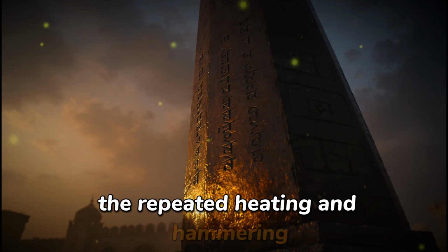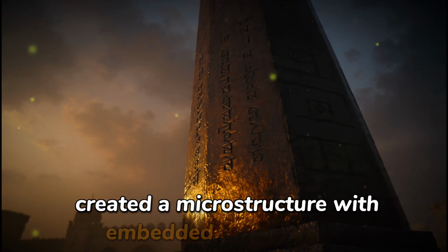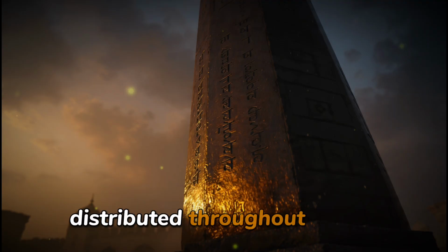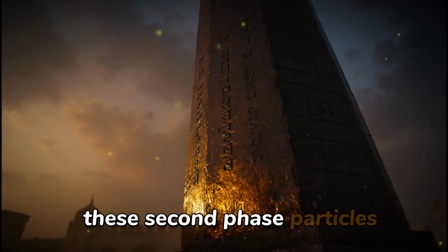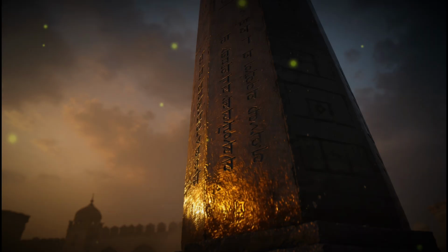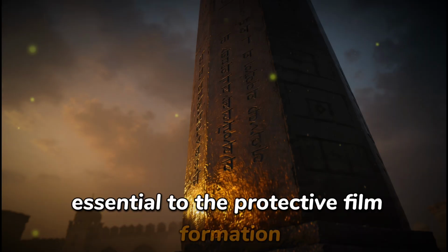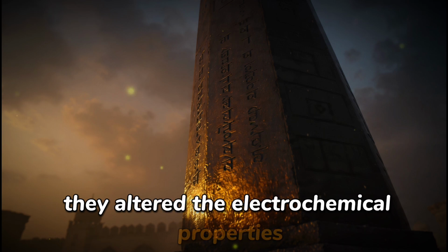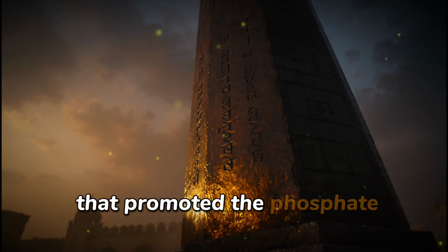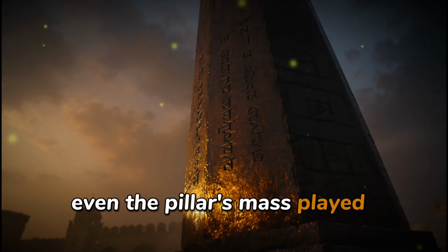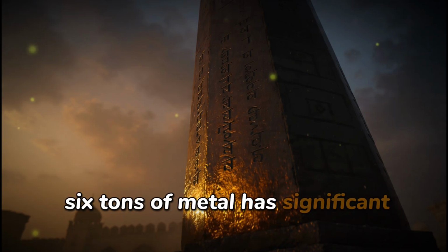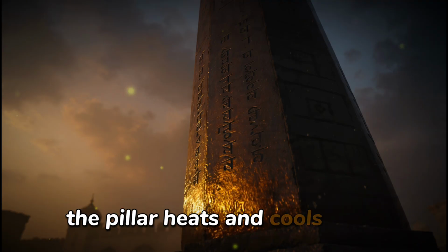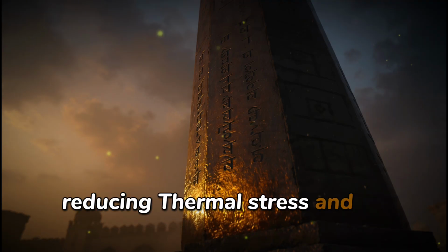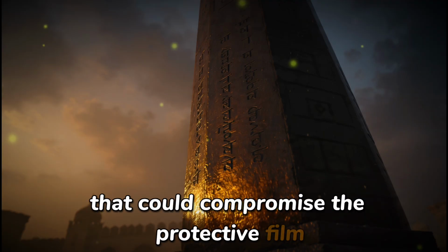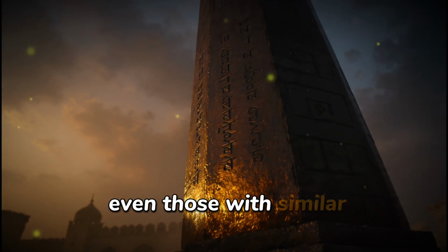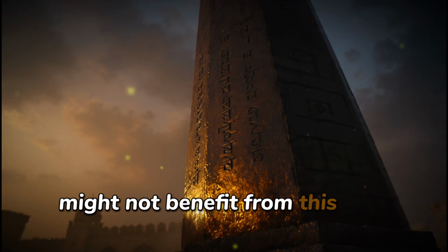The repeated heating and hammering created a microstructure with embedded slag particles distributed throughout the iron. These second-phase particles, typically considered impurities, were actually essential to the protective film formation. They altered the electrochemical properties of the surface in ways that promoted the phosphate layer's development. Even the pillar's mass played a role. 6 tons of metal has significant thermal inertia. The pillar heats and cools slowly, reducing thermal stress and the formation of cracks that could compromise the protective film. Smaller iron objects, even those with similar composition, might not benefit from this mass effect.